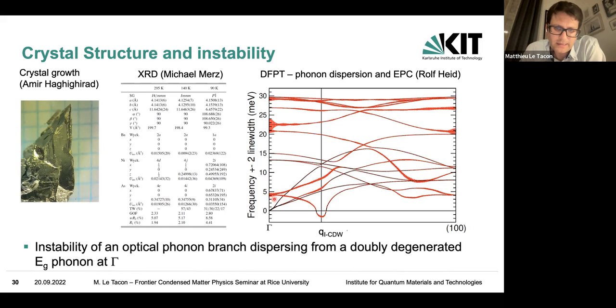And what you find is that if you follow that branch, it's a doubly degenerate branch at the gamma point, and this happens to have the Eg symmetry. So the branch which is getting soft is in fact the same branch which is splitting in the Raman experiment. What's already interesting to notice here is that Rolf can also calculate the electron-phonon coupling, and the widths of the peak here, the red widths, represent the contribution to the electron-phonon coupling. This mode exhibits a bit of electron-phonon coupling, but it's far from being the dominant channel. The dominant channel is clearly that one, and this is the A1g mode.